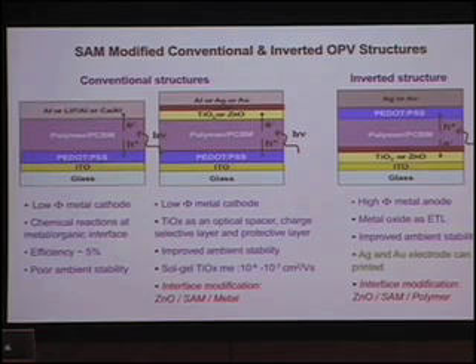So in our case, we try to substitute that: instead of titanium oxide, we use zinc oxide, which has about 4 orders higher mobility for electrons. And then on top of zinc oxide, we can grow a layer of the SAM to help collect the electrons. So this is one based on the conventional approaches.